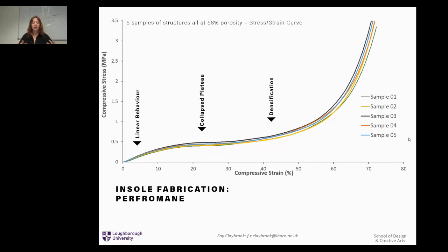So in the present study, to compare the compressive properties between these elastomeric scaffolds that were designed, we defined the maximum compressive stress. So a point where the porous test structure began to collapse while permanent dense deformation was absent. So in a rigid material, it would go linear, collapse, plateau, densification, or it would snap and break. Whereas in this material, due to the air being collapsed out of the structure, I'm defining it between the linear behavior and the collapse plateau. So if you made a little triangle, that's going to be where the maximum compressive stress is. So it doesn't go into the densification, getting rid of all of the designed gaps and air out of the structure, because then it would just base off the solid material. Hopefully that makes sense.